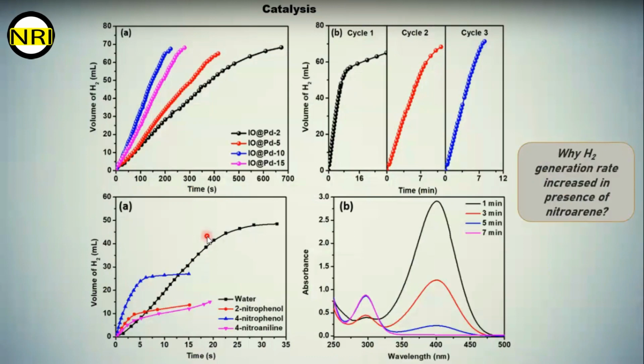After characterizing the catalyst, we have used it for the catalysis reaction, and first we started with the ammonia borane hydrolysis reaction. This is the hydrogen generation graph, and we can see that the hydrogen generation rate is increasing with increasing palladium loading, up to 10%. After that, for the 15% sample, the rate is decreased. This is due to the surface area of the catalyst, because when the surface area is more, the rate will be more. When surface area is less, reaction rate will be less. This is the common relation between surface area and catalysis.